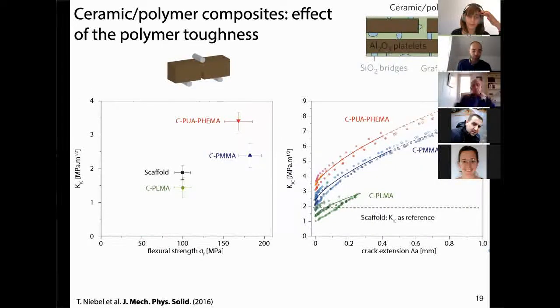So, okay, it kind of makes sense at the beginning. And we can see the tougher polymer here has the higher toughness and more or less the highest flexural strength. And if we actually plot the resistance to crack propagation, so this time we do an R-curve, if you plot the value of toughness as a function of the crack extension from this initial defect, you can see that, so that's where the crack initiates, that's the value at which the crack initiates.